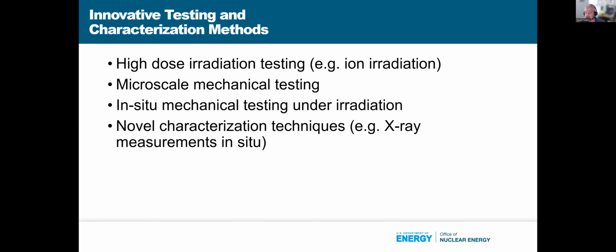I mean, they're not not out there, but improved and qualified to get good data from either high dose ion radiations or from doing microscale mechanical testing. And I connect those two, but I should also say that if we can apply microscale mechanical testing to neutron irradiated materials, that is a help as well, because of course, after irradiation, these materials are highly radioactive. And so we can work with smaller amounts of material and keep the dose down. There's a lot more that we can do with characterizing and testing those materials.